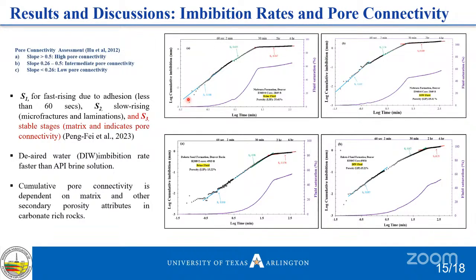You see what's going on here at initial time. You see that there is fast rising of the fluid in the formation due to adhesion within less than 60 seconds, which is what you see here. And then there is another one which is slower rising, as you can see. And the third one is this one, which is the stable stage. And this is what determines the pore connectivity, because at this point, it is the matrix porosity that really plays a role. In the second stage, it could be due to microfractures and laminations. And because these reservoirs can be considered as unconventional, they have both fracture and matrix porosity, which can be combined for more effective porosity.